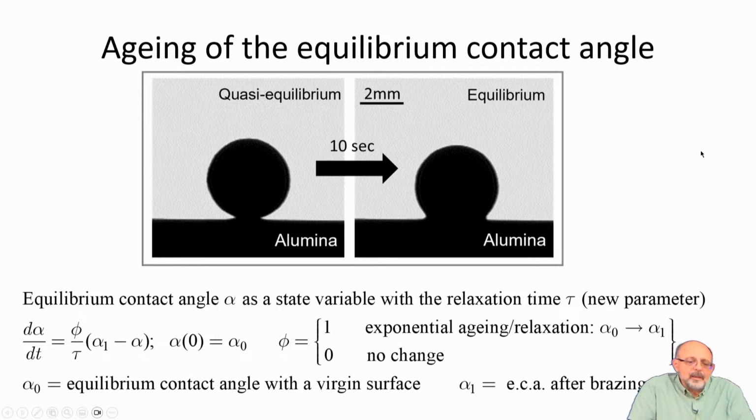Okay, but then let's try some shorter time scale. Let's try a little ball, a little sphere. If you take this same alloy and shape it into a sphere, well, it was not a sphere initially, it was a cube. But if you melt it fast, it makes a sphere, with a contact angle here of roughly 170.